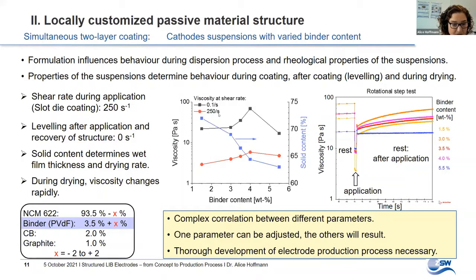So the solid content of each suspension has to be adjusted in a way that the viscosity at this shear rate, which is shown here in red, is appropriate for application. And because of this, the solid contents of the individual suspensions, shown here in blue, can result in very different values. As a consequence, to reach the intended dry mass loading, the wet film thickness of each layer has to be adjusted accordingly.